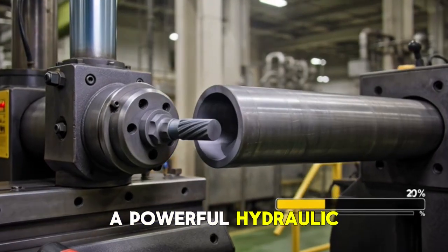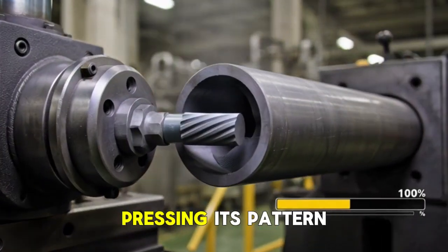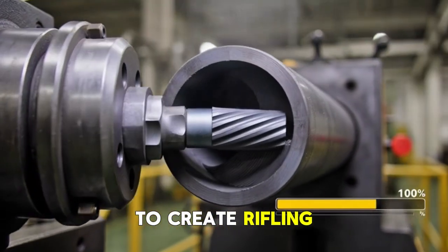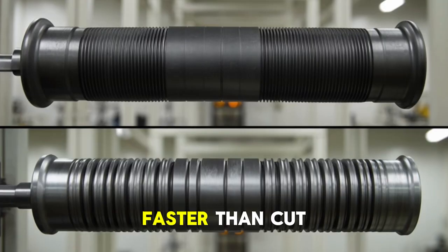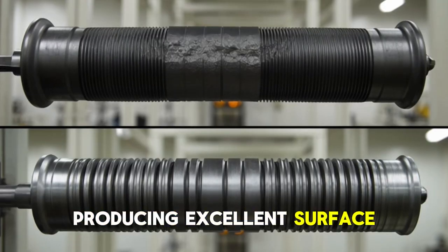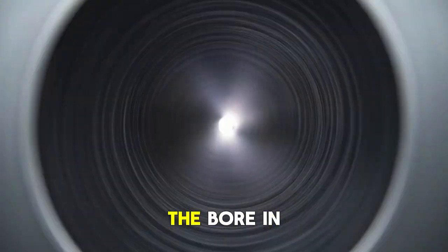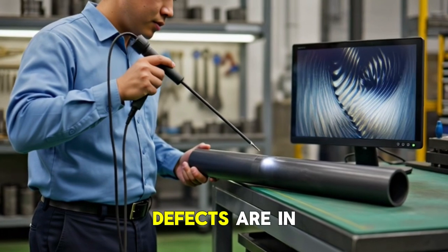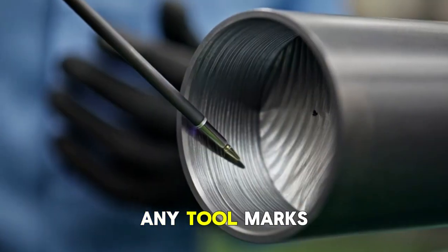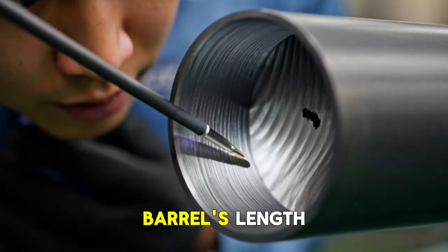A powerful hydraulic ram pushes the button through the barrel bore, pressing its pattern into the surface to create rifling grooves through cold forming. Button rifling is faster than cut rifling, producing excellent surface finish and wear resistance by work hardening the bore in a single pass. The bore is inspected for rough areas or defects in the interior, and any tool marks. The surface should be uniform throughout the barrel's length.